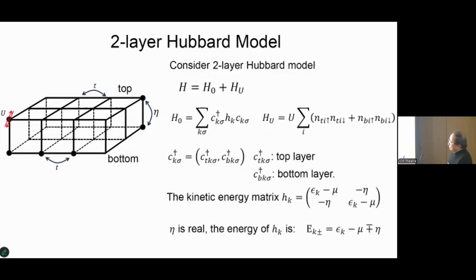So right now I want to focus on a simple model. This is a two-layer Hubbard model. It's standard: I have a kinetic energy part and the Coulomb interaction U on site. That means I put two electrons on the same site of this double layer system, and I will consider U to be large. And the kinetic energy is just given by this, and I consider eta to be the hopping between these two layers. In the limit of large eta, I have a very strong band splitting, so the energy of this H_K can be written very easily, just plus minus eta.